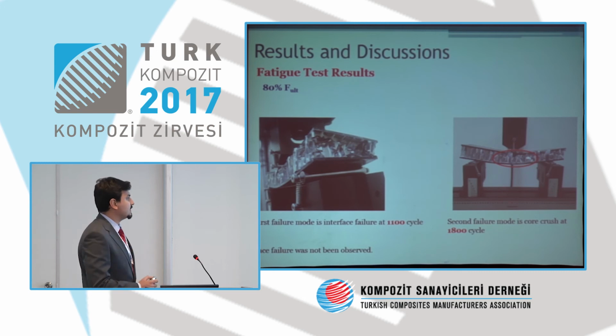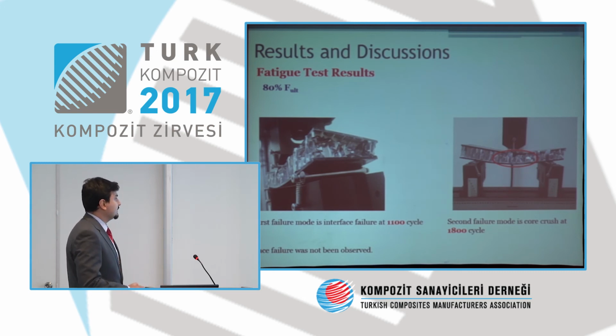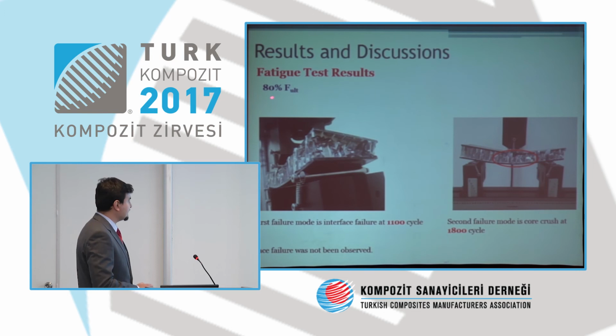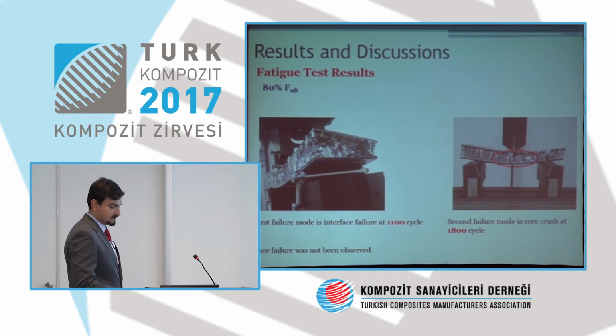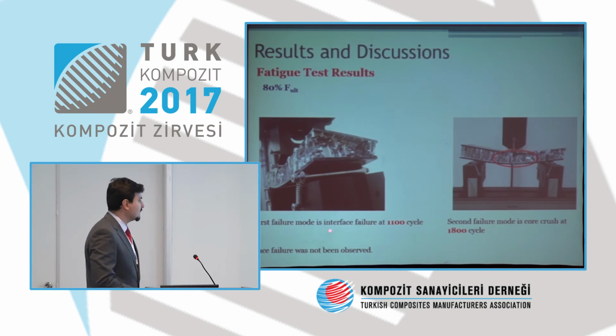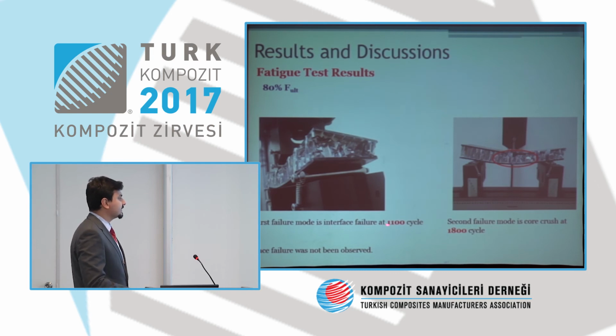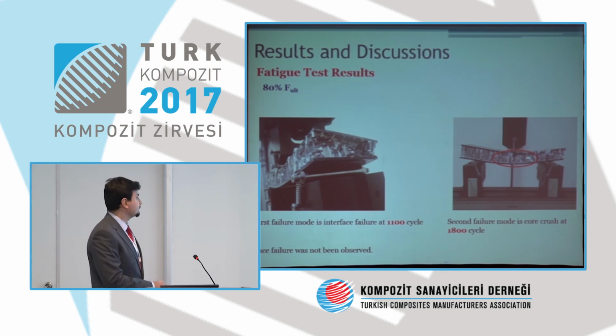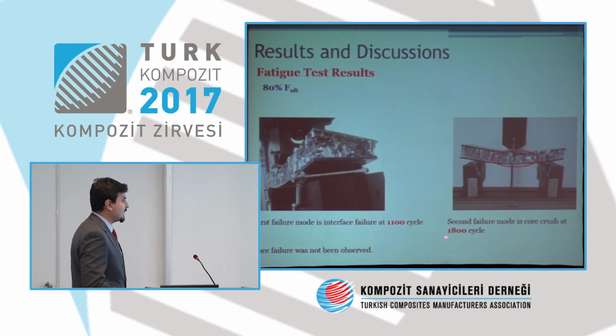Then these are our fatigue test results. It's for 80% of ultimate force. First failure mode is changed here. We obtained the interface failure at 1,100 cycle, as you see here. And it occurs at the edges. And the second failure mode is core crush, at 1800 cycle.